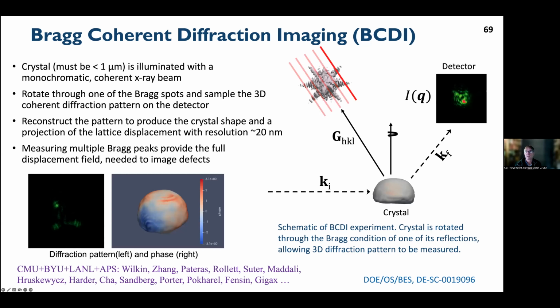Anyway, not to make too much out of this. The basic idea is if your crystal that you're diffracting from is small enough, meaning it fits within the coherence length of the X-rays that you have, which at the moment at moderate X-ray energies, 34 ID, for example, is about a micron, then if you scan through an individual peak, what you see are fringes. And obviously, I'm showing you a sort of idealized example of this.